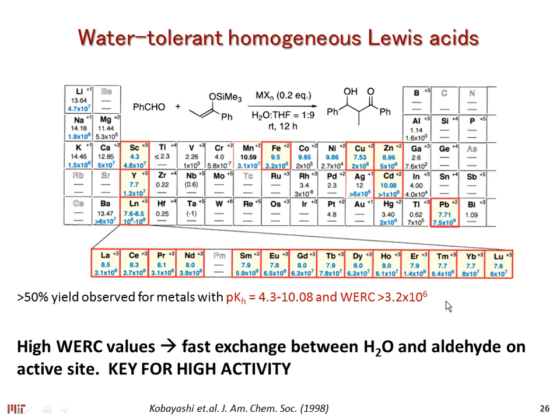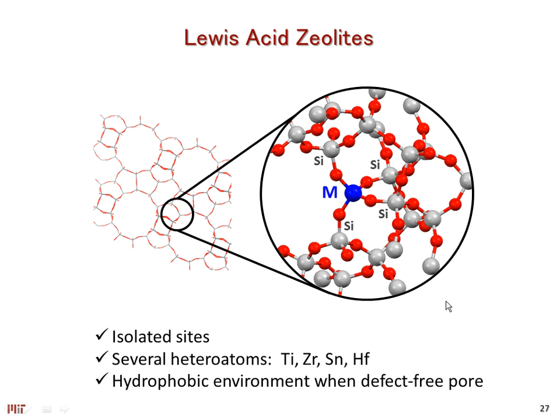of the metal. So looking into those particular parameters, we're very interested in looking now at metal centers embedded in a zeolite that has a hydrophobic pore to start activating some of these groups. For example, isolated heteroatoms such as titanium, zirconium, tin, or hafnium don't impart a charge imbalance into the framework, as a trivalent metal like aluminum in a zeolite would, so you don't have any Bronsted acidity. But they have open coordination sites, so they can accept pairs of electrons, and these will effectively act as Lewis acids. The important thing is that water doesn't coordinate so strongly that it quenches the Lewis acidity, and that's where the hydrophobic pore comes into play, alleviating some of this very strong coordination to the metal center.